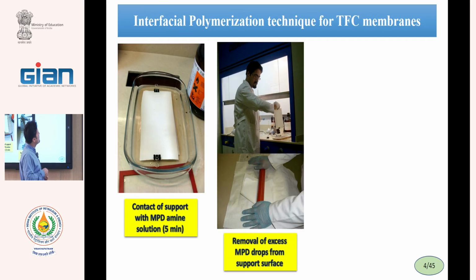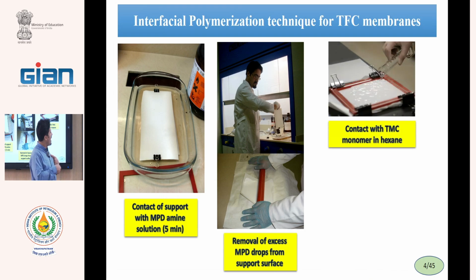In the lab, after preparation of the polysulfone support, we first immerse the support in MPD solution. We must give time for filling of the support pores with MPD aqueous solution. Usually 5 minutes, 10 minutes is used. After a certain time, we take out the membranes, and with a plastic roller, we remove the excess MPD drops from the membrane surface. We roll only one time, and rapidly go to the second step, or we can put the TMC hexane solution on the membrane surface.